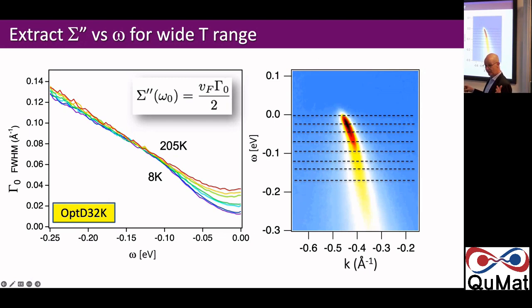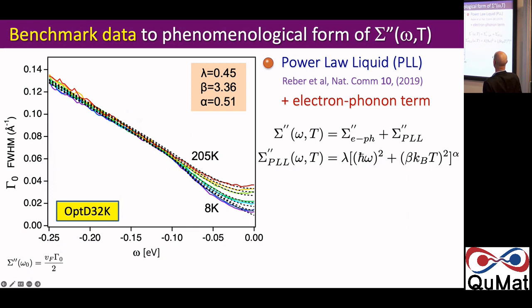So now we want to do some fit to it to extract some theory parameters. So there's a suggestion in the literature back in 2019 that you can describe the electronic self-energy as what's called a power law liquid. It's phenomenological. It's not based on a microscopic theory, but says we have some power law describing the frequency and temperature dependence of the imaginary part of the self-energy. Frequency dependence goes as frequency squared plus some constant times the temperature squared, and all of that to some power alpha. So if you want to have a Fermi liquid, alpha will be 1, and you have omega squared T squared. If you have alpha of 1/2, you will have omega T.